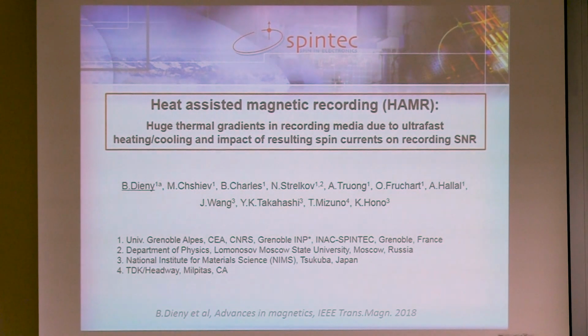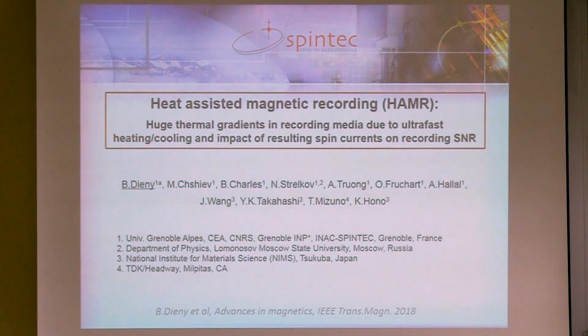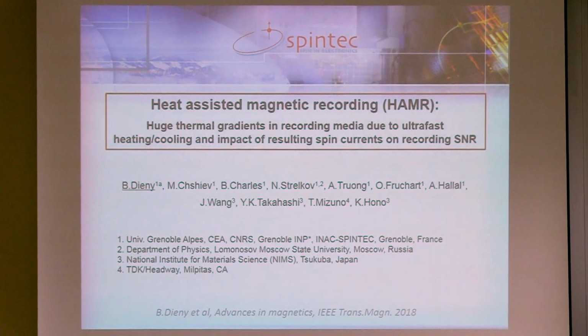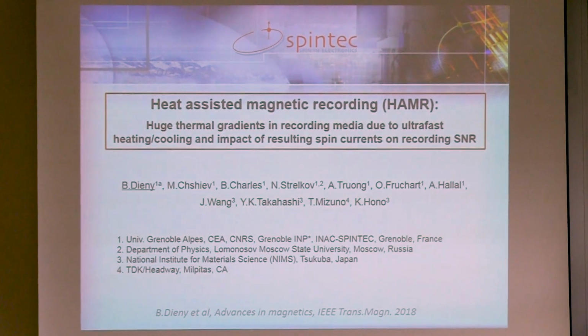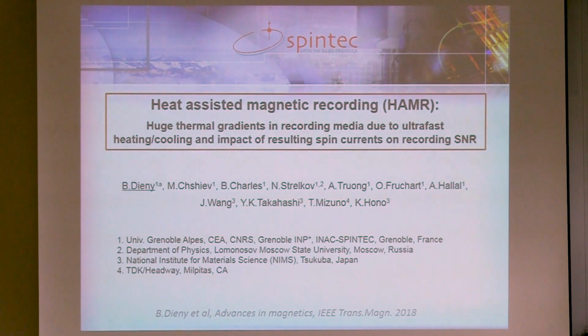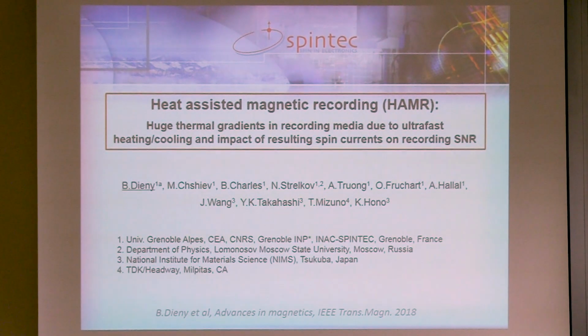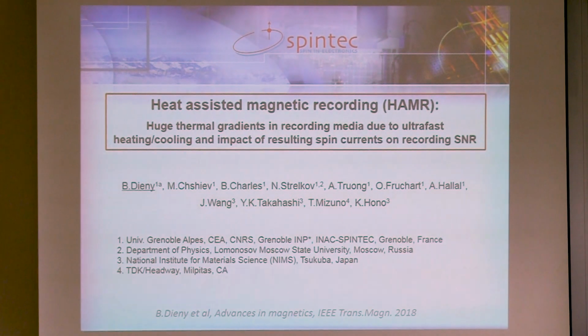So why am I going to talk about heat-assisted magnetic recording? Because I will show that thanks to the combination of very local heating with a plasmonic antenna and the motion of the media in a hard disk drive, it's possible to induce ultra-fast cooling of the magnetization in the media in which we are writing the information, and we can thereby create very strong thermal gradients in the media, up to values like 100 Kelvin per nanometer, which is a very, very huge thermal gradient.